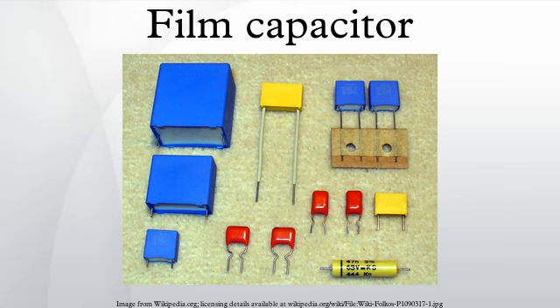Most power capacitors, the largest capacitors made, generally use polypropylene film as the dielectric. PP film capacitors are used for high-frequency high-power applications such as induction heating, for pulsed power energy discharge applications, and as AC capacitors for electrical distribution. The AC voltage ratings of these capacitors can range up to 400 kV. The relatively low permittivity of 2.2 is a slight disadvantage, and PP film capacitors tend to be somewhat physically larger than other film caps.